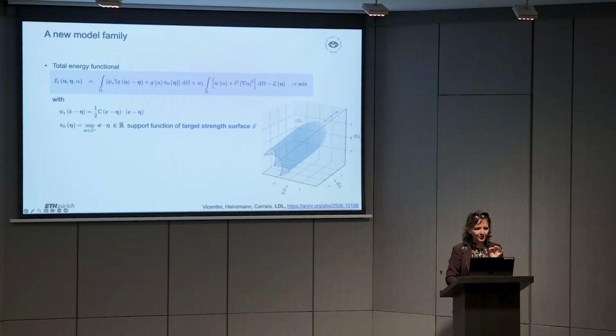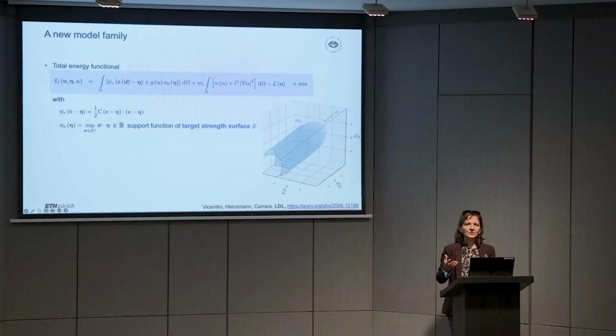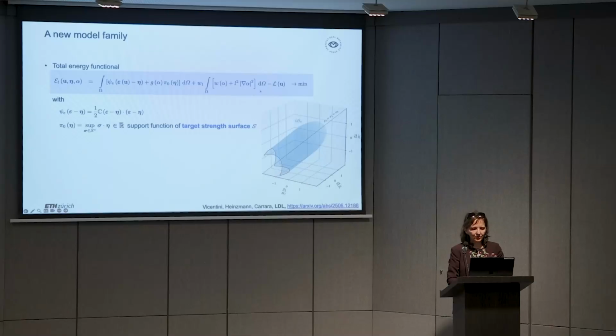So essentially now you see that the elastic strain energy density is no longer multiplied by the degradation function, and it depends on the difference of the total strain and the eigenstrain. So essentially this difference is the elastic strain. So we have a sort of additive strain hypothesis, much like you do in plasticity, for instance, right? And then we have an additional energy contribution, which is degraded by g of alpha. And this additional energy contribution, if you were in plasticity, this would be the energy that is associated to plasticity. Here we are not in plasticity, but we have a cohesive framework. So we still have a similar contribution that is due to the inelasticity, let's say. And this contribution is degraded by multiplying it by the degradation function g of alpha. The rest is the same. So let's say the fracture part is identical to the classical one. Then, of course, you have minus the work of external forces.